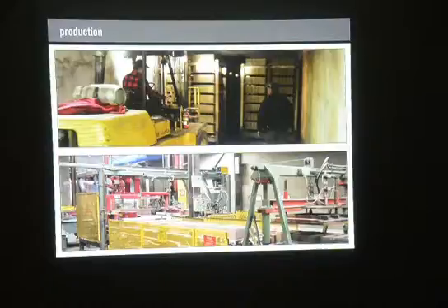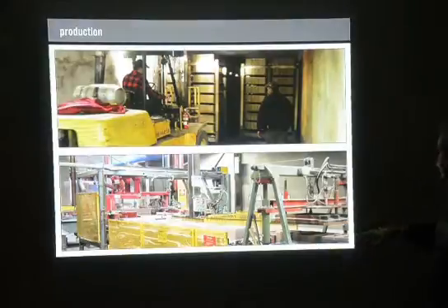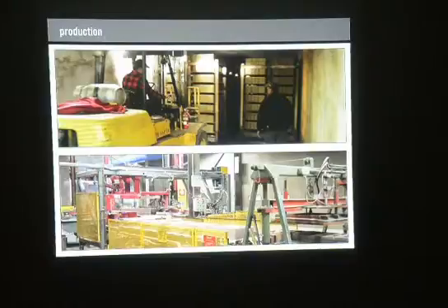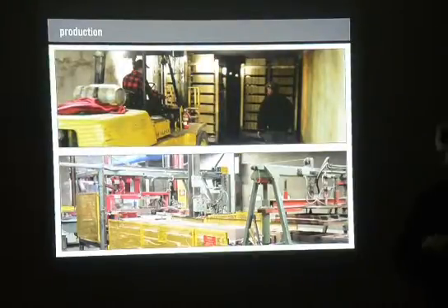So as you can see, the forklifts are transporting them in and out, okay, and then there's an assembly line that has vibration and compaction until they get to the right side of the photo, and then by hand, they're inspected. Now, are there inspectors along the way? Yes, there are. I work with people, not only in Oceanside, but Riverside, where I was earlier today, and Stanton, which is the corporate headquarters, and we had our plant in Stanton about a month ago, where they have tape rules. They have measuring tapes to make sure that an 8-inch block is 7 5/8.